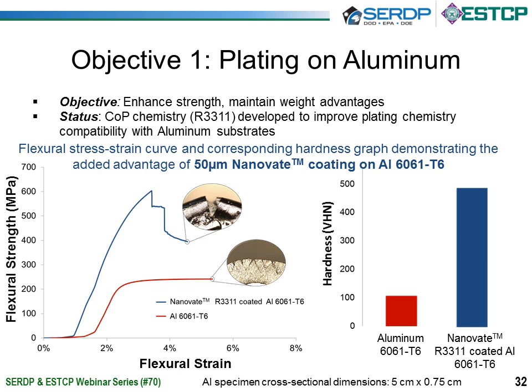But if you're masking certain areas when you're coating aluminum, if there's any issues with the mask, then you could have some corrosion. So we looked at modifying the chemistry specifically for plating onto aluminum substrates, and were quite successful and developed a slightly new process, which we call the R3311, which was able to successfully coat onto the aluminum without any risk of damage. So what we show here on this slide is a comparison of the hardness between aluminum and the cobalt coating, showing a very high increase, so that would be better surface durability.